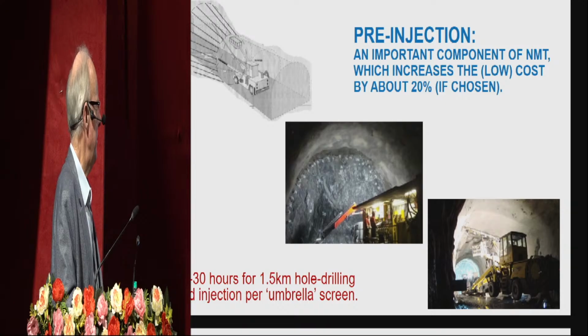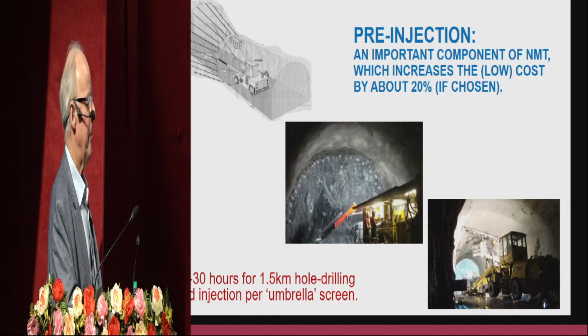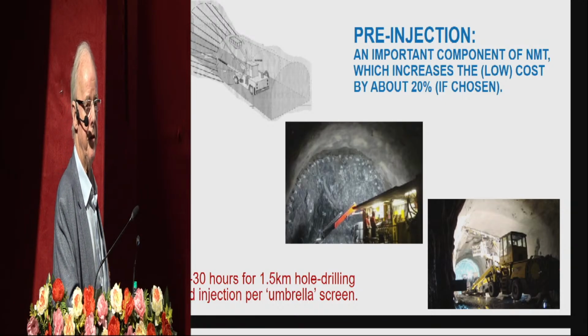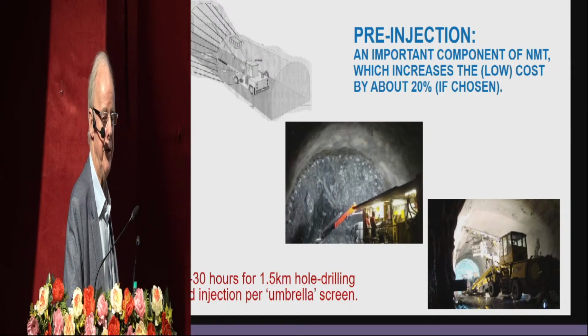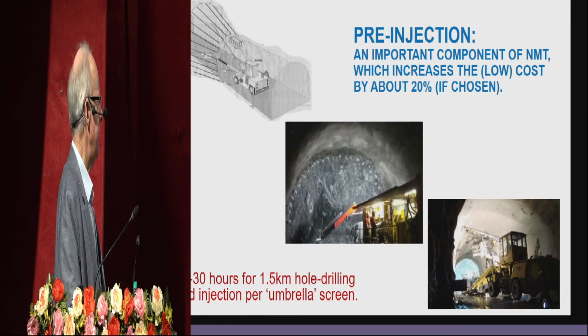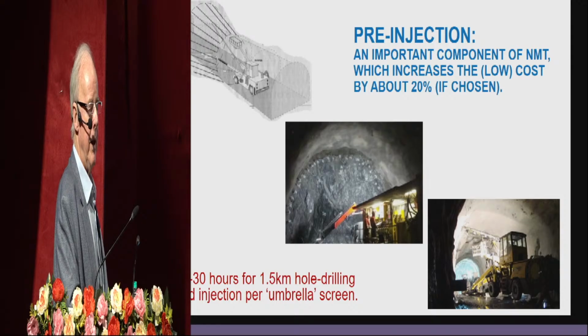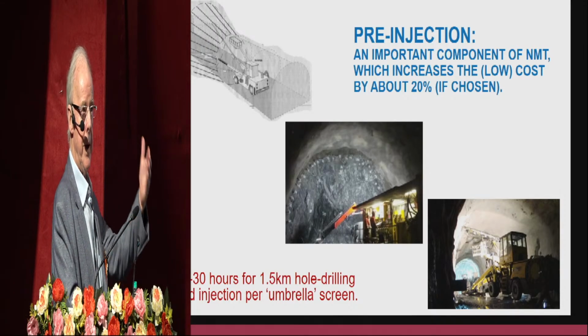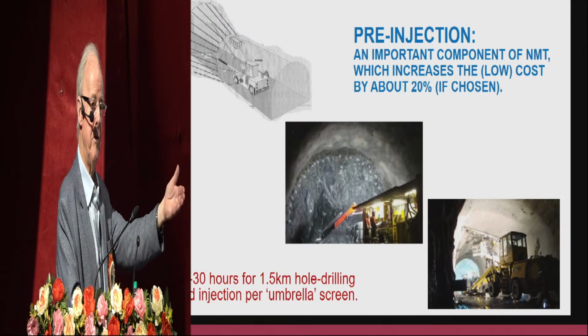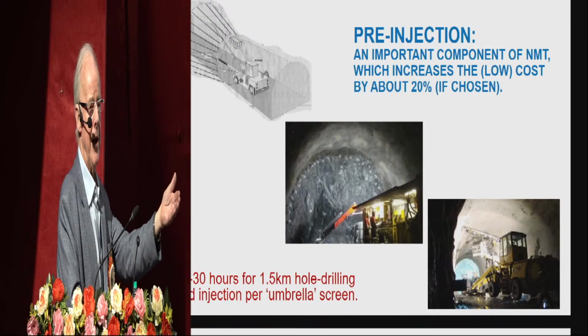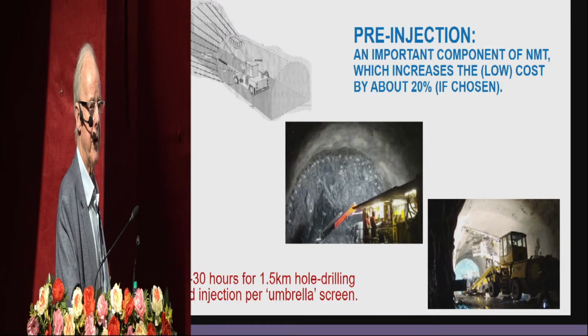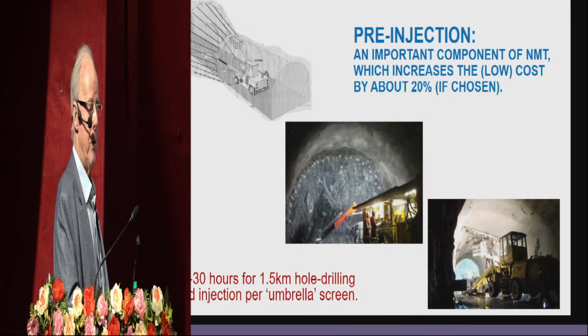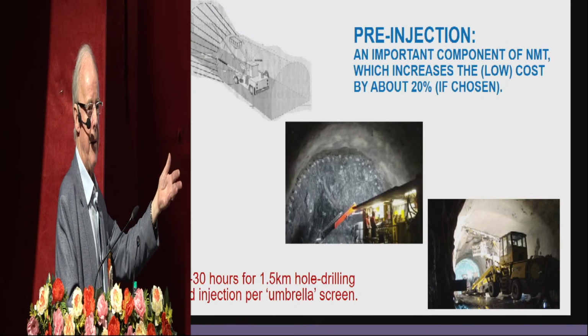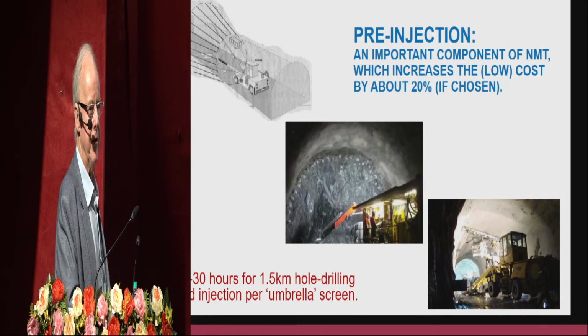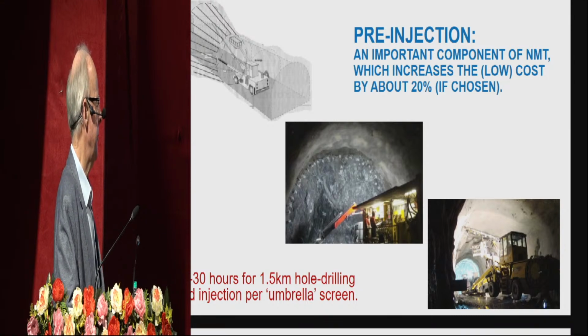So in Norway, we've done lots and lots of pre-grouting. We used to make a lot of mistakes like 40 years ago, and it got better and better 20 years ago, and now they can have like 1 or 2 liters per minute per 100 meters inflow, and that more or less prevents the drawdown of the groundwater. If you go like 4 to 10, then you're going to get some damage. 10 and above, 10 liters per minute per 100, you're going to get damage.